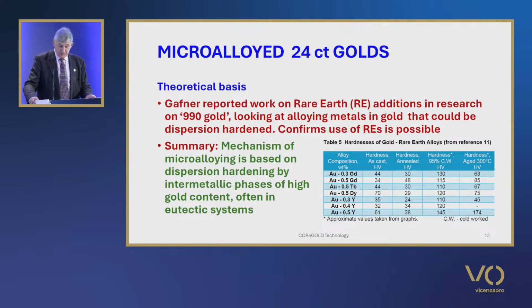They were also cold rolled up to 95% deformation and subjected to age hardening treatments at a range of temperatures. The table on the slide shows the hardness values attained for gold alloys containing 0.5 of the alloying metal or less. From this work, it can be seen that the annealed hardness is little different from normal pure gold, although cold work material is much harder and in the range of improved 24-karat gold materials. Age hardening heat treatments are not very effective at these low concentrations, with the exception of the 0.5 weight percent gold yttrium alloy,